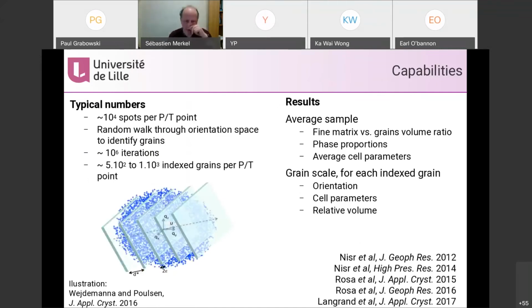Now, how do we do that? With typical capabilities, we are working with about 10,000 diffraction spots per pressure, and then we do random walks through orientation space to locate the grain. We typically do a million trials, and that allows us to index on the order of 500 grains, sometimes less, sometimes more, at each pressure. And then for each grain, we get their orientation, their cell parameters, and their relative volume.